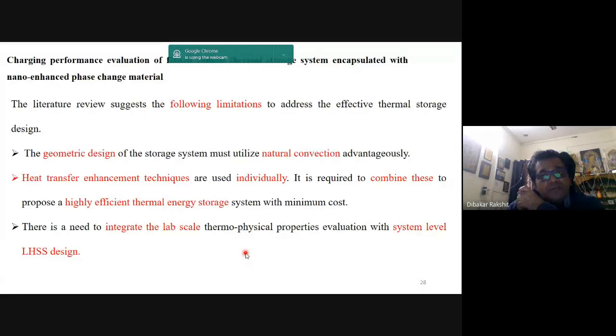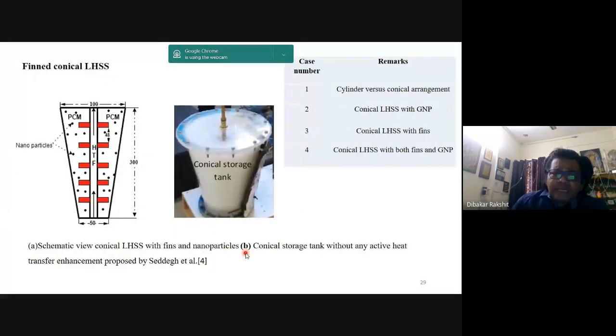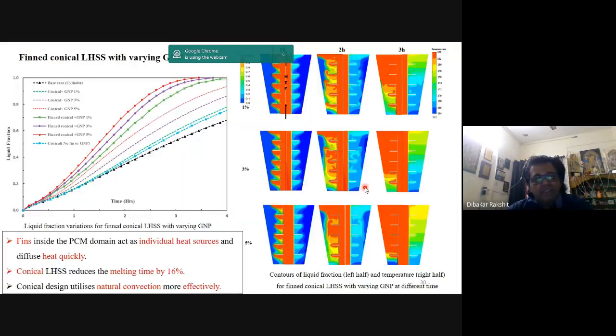It is also done for this type of structure, where the shape of the thermal battery was changed from cylindrical to a frustum of a cone, say conical. So this was the structure which we attempted to study, where we have taken the effect of the conical arrangement and tried to find out its effect in contrast to the cylindrical arrangement we started with. And then again we did all the combinations of mixing with graphene nanoplate for this latent heat energy storage system, introduced fins, and then a combination of both. So these were some of the candidate solutions which we approached to study through this CFD analysis.